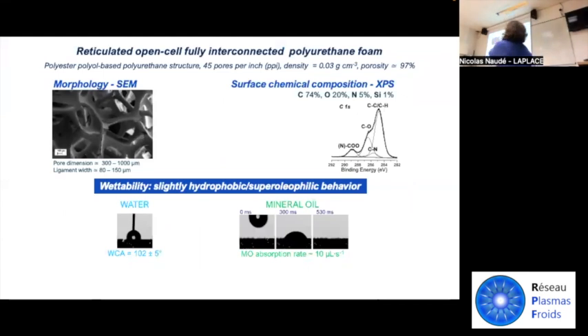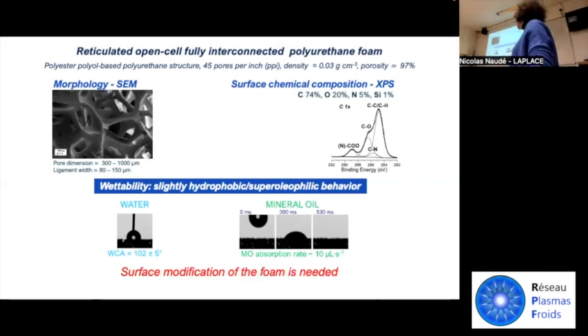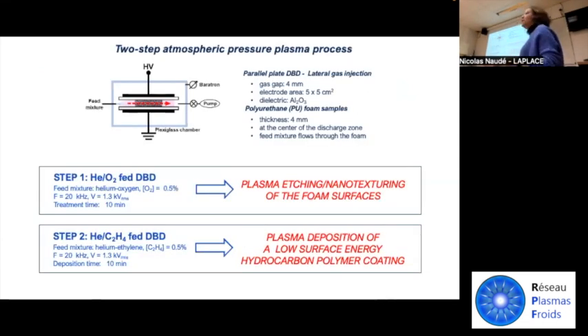Let me focus on the wetting properties of the pristine foam. The pristine foam is super oleophilic, so it absorbs mineral oil quickly, while it is slightly hydrophobic. It presents a water contact angle of 102 degrees. In the application of the material, this is not enough to obtain real oil-water separation with high selectivity, and the surface modification of the foam is needed. We optimized a two-step plasma process in this case.